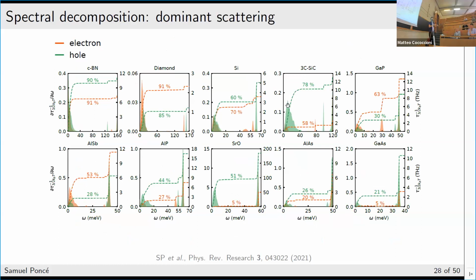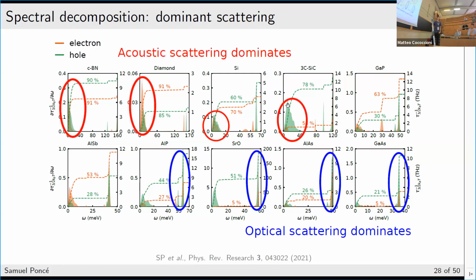What is nice with a general framework like this is that you can also understand the microscopic origin of this mobility. What I'm showing here is the spectral decomposition. What it means is: what are the phonon modes, so this is the phonon frequency, that contribute the most to the scattering, so to the lowering of the mobility. And you can see that it's very material dependent.